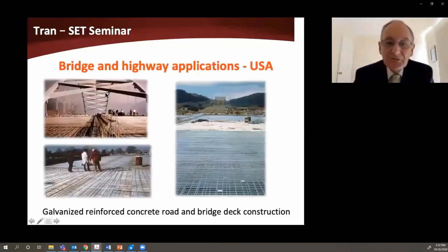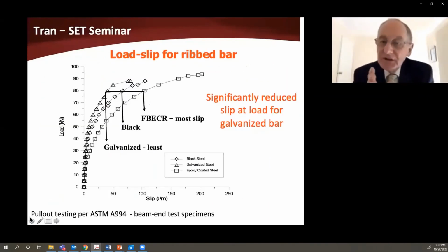The reason for this, again, is because there is very significant adhesion of the cement to the galvanized surface. There is virtually no adhesion with fusion bonded epoxy bar, and there is very limited chemical adhesion of cement to black steel bar. But galvanizing is very much better than that. So the bond strength is as good as, if not significantly better than, black steel. The slip is significantly less.